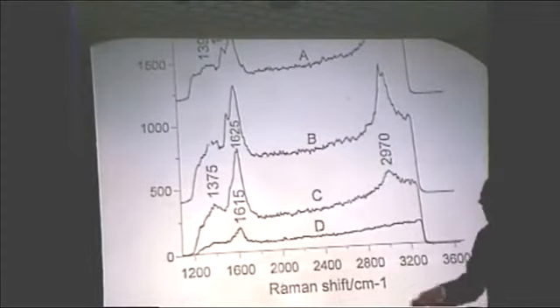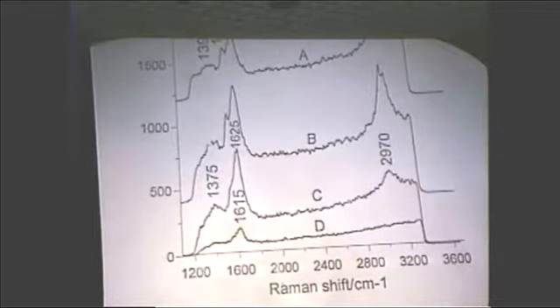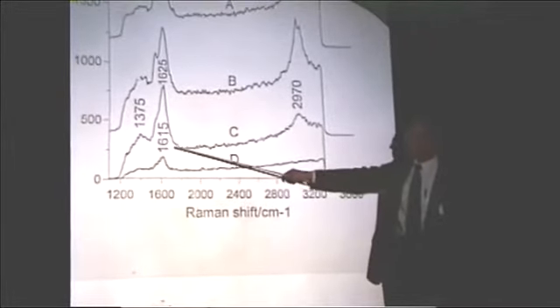This band position is representative of what we would expect for polyaromatic type of coke on the surface. So there is a relatively small fraction of the coke on the ZSM5 which is polyaromatic and doesn't come off, but the majority just comes off by heating in helium. So it's what you'd expect for a zeolite which is resistant to coking. The coke comes right off.